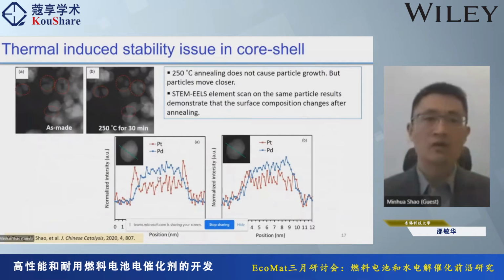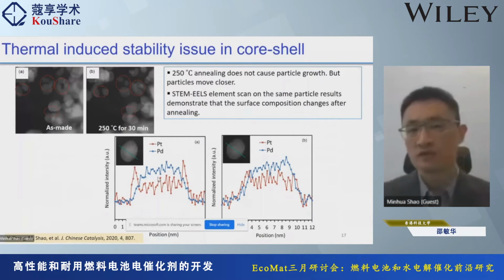Another phenomenon that we are quite interested in is the stability of the core shell. The first thing is the thermal stability, because we are talking about a core shell that is actually monolayer scale. So it's possible that the palladium and the platinum can mix together on the surface and form an alloy on the surface. We wanted to understand this phenomenon: at what temperature can this mixing already occur? This is very important when we prepare the ink. Before we put this catalyst in the fuel cell, we typically use different mixing methods, and that can create a high local temperature.